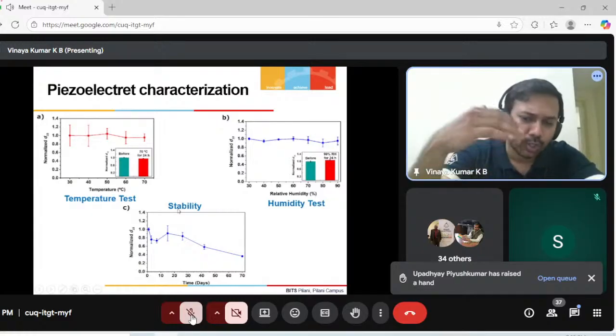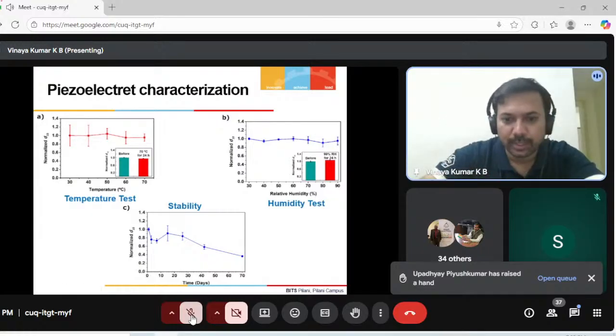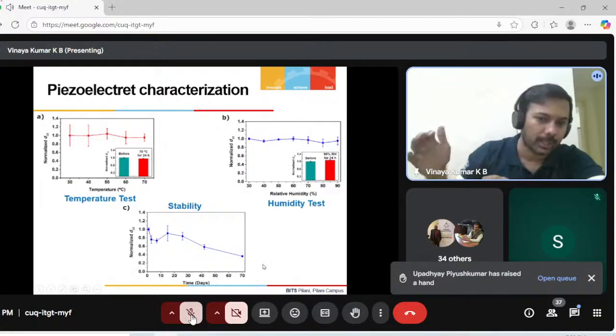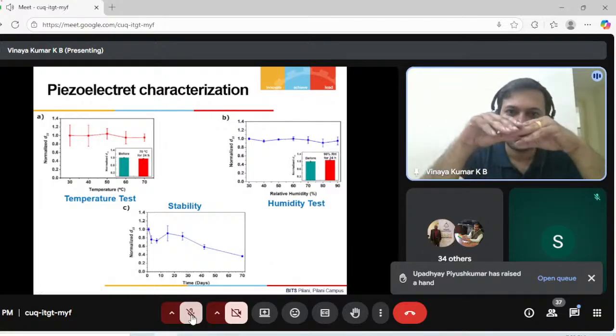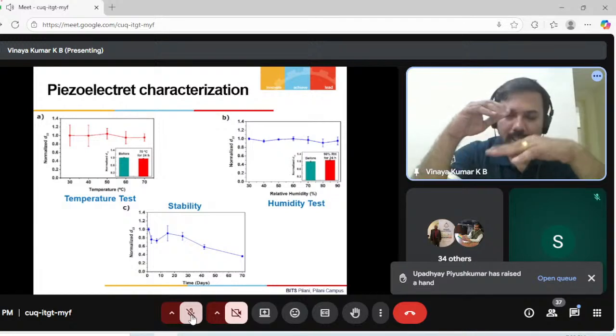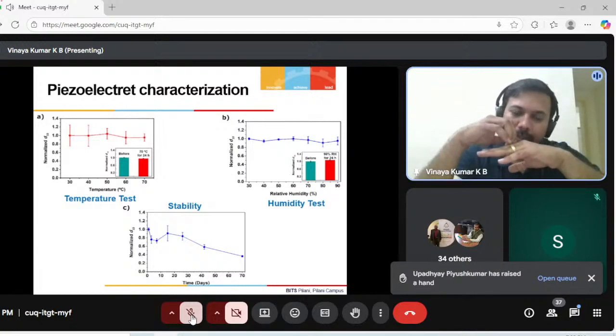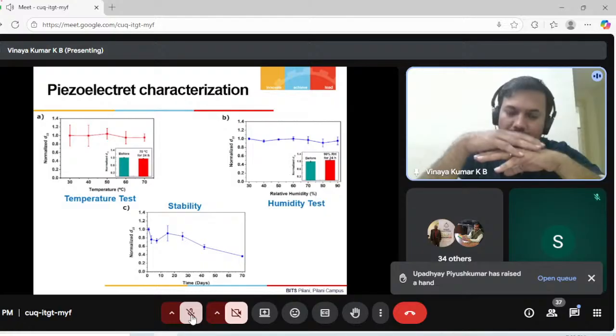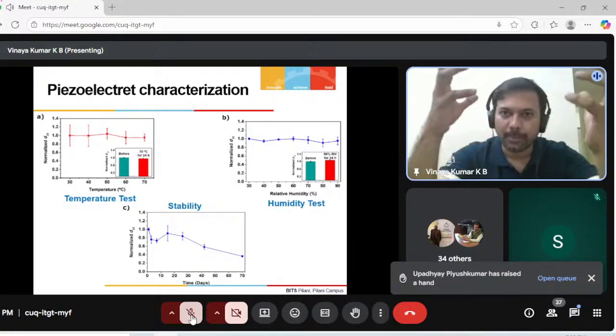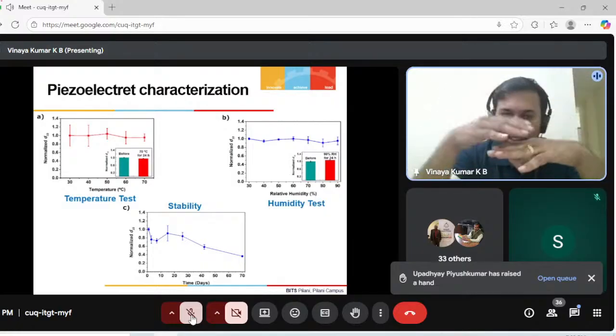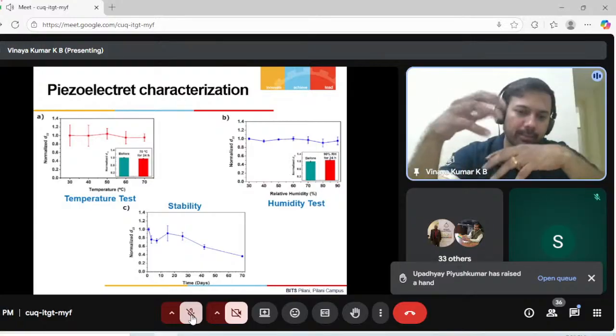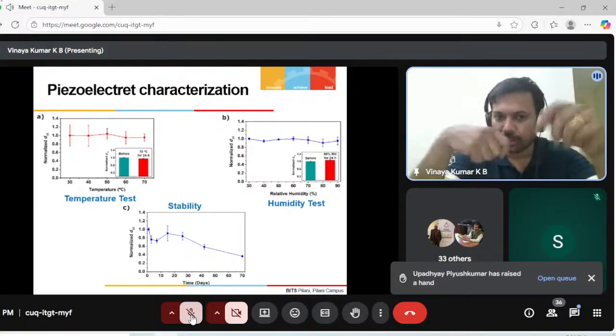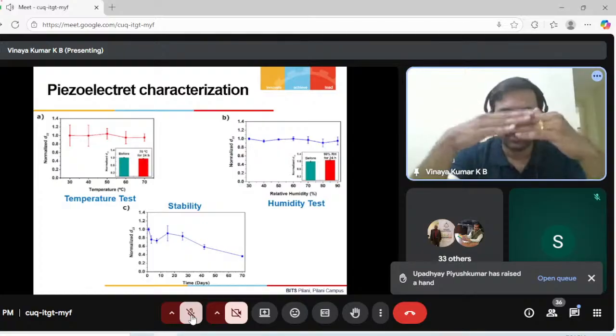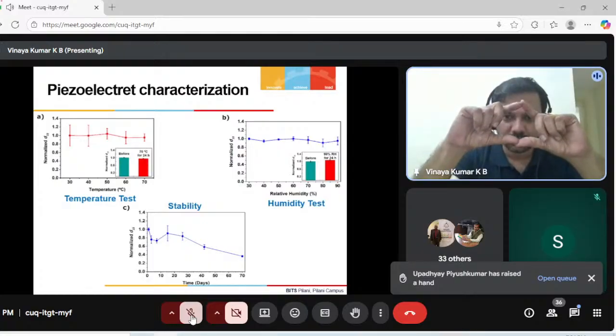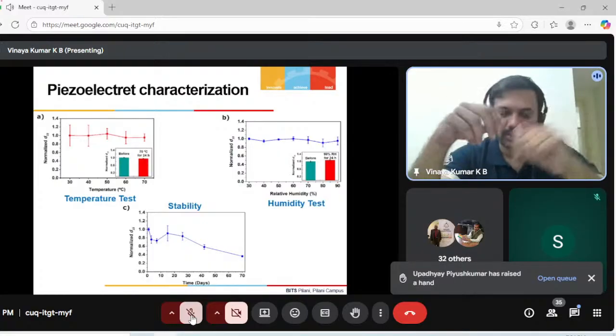But one of the problems we faced in our research is with respect to the stability of the device over time. Like I said, this is the device where you will be using a charge trapping on the insulating material. The charges on the surface, right? With eventually being exposed to the ambient, there is a good chance that the charges are going to degrade because of the wear and the number of times we use it and stuff like that. Because there are positive and negative charges which are very close, there may be a connection between them.